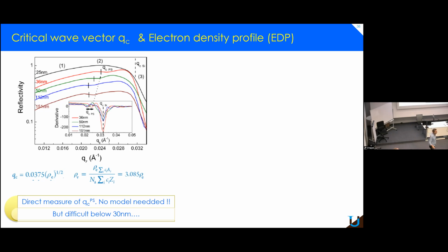Polystyrene, people work on polystyrene nanoparticles. Do people look at the densities of those nanoparticles? In principle, this could be a nice experiment where you don't have a problem with the surface. Yes, actually, the problem is that there are a lot of things different inside due to polymerization, initiator, things like that. But I should admit that we didn't find anybody that thought about measuring the density of polystyrene. Maybe there are, but we are not aware. But yes, it's probably a good point.